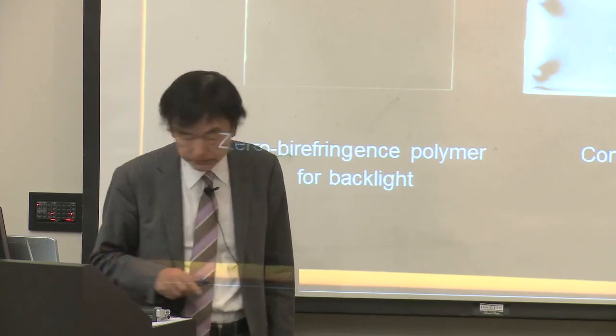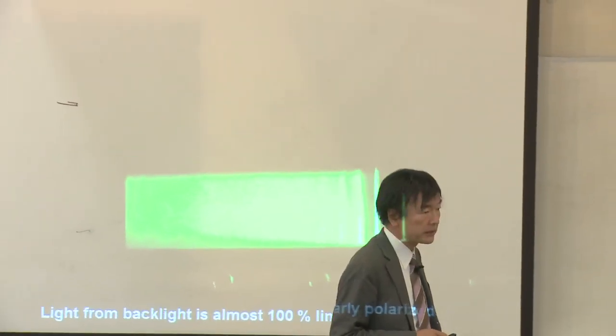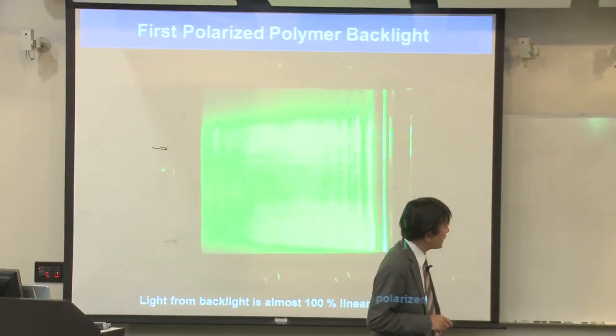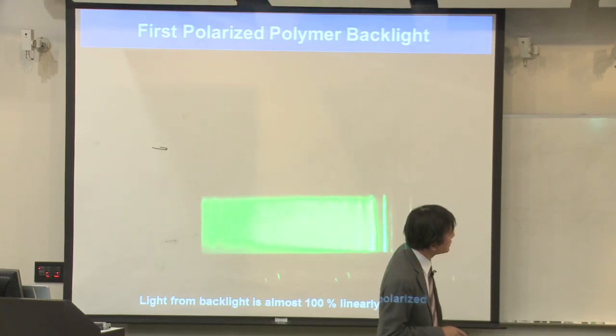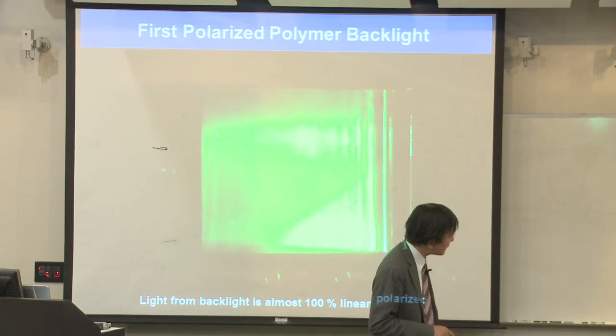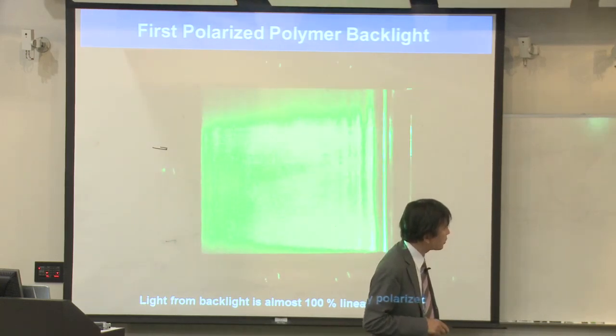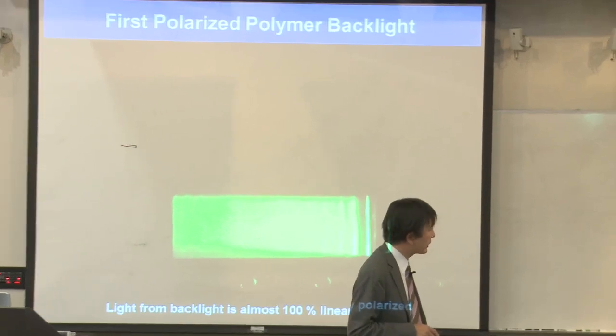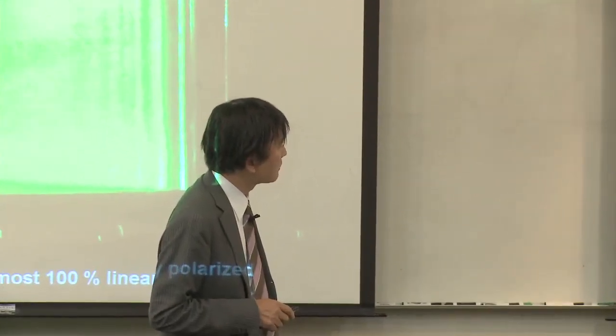Okay, this is a demonstration. Now we made the zero birefringence polymer backlight. Here we go. This is the first polarized polymer backlight. Okay, now we rotate the polarizer. Now it's completely dark, but this is the backlight. The light from the backlight is almost 100% linearly polarized. Then when the angle becomes perpendicular, it's completely dark. So this is the first demonstration of the completely linearly polarized backlight. With using this, the brightness becomes 200 times.